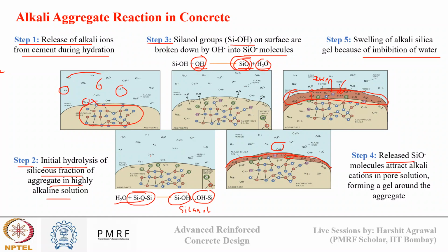So we have this reactive silica which converts into silanol groups in the presence of moisture. In the presence of highly alkaline medium, the silanol groups break down into SiO minus. This SiO minus attracts alkali ions due to charge difference, and they form a gel over the aggregate surface which absorbs water, which is known as imbibition of water, and they generate tensile forces due to swelling. And these expansive forces or expansive gel cause cracking in concrete.